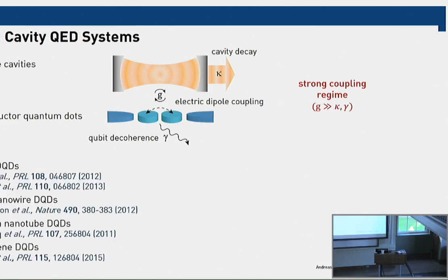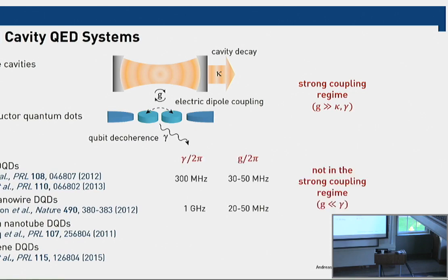And there were early experiments starting maybe in 2010, 2011, where people were trying to make different types of double quantum dots in different material systems, like gallium arsenide gate-defined dots, indium arsenide nanowires, also using carbon nanotubes and even graphene. The experiments that were done in those days all managed to achieve some dipole coupling between the electrons that tunnel-couple between these 2 dots. But none of the experiments actually reached the strong coupling limit. The reason was that the decoherence rates of charges in these double dots were quite large, typically on the order of a few hundred megahertz or even gigahertz.